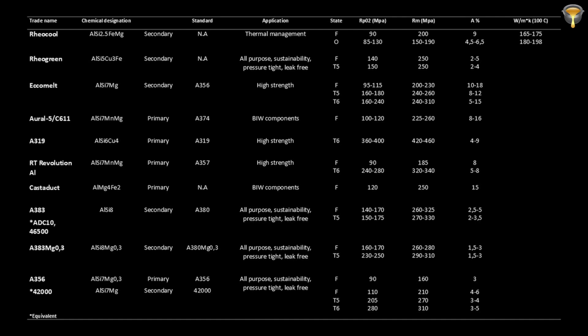I would like to change the subject to alloys. You see this table, and again, all these misconceptions that you see out in the market. But if you look at the chemical composition, you'll find alloys from 2.5% silicon up to actually 9, the A383, for example. And a few words on them. You see something called Rheocool, Rheogreen. These are developed inside Comtech for certain applications, especially for either telecom or, I would say, not traditional car makers, because there is no standard here. The reason why they're called Rheogreen and Rheo Standard is that they have extreme low carbon dioxide emission rates from the production of the alloys. 100% recycled.